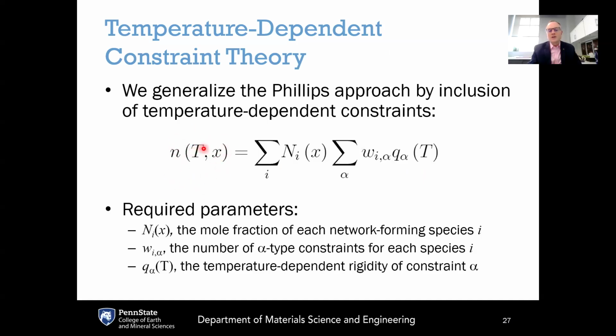And this number of constraints per atom is going to be equal to a double summation, where the outer summation is over all the different species of the glass, all these species I, and their corresponding mole fractions. So n sub I would be the molar fraction of each of the species. That is only a function of the composition X. And then for each one of those species, we have a summation over all the different types of constraints alpha. So these would be all the radial constraints and all the angular constraints. And each one of those types of constraints alpha would have a number of constraints associated with it.